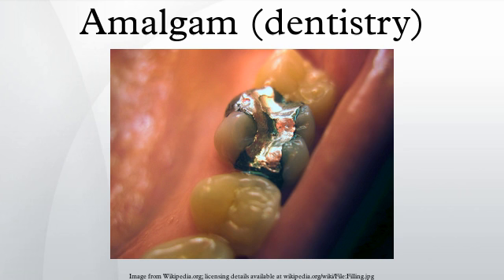Metallurgy of amalgam. To fabricate an amalgam filling, the dentist triturates a silver base alloy by mixing roughly equal parts of shavings of the alloy with liquid mercury in a mortar and pestle or other grinding device until the shavings are thoroughly wetted. The silver alloy is typically 40 to 70% Ag, 0 to 30% Sn, 2 to 40% Cu and 0 to 2% Zn. The dentist packs the plastic amalgamation, before it ages, into the cavity.